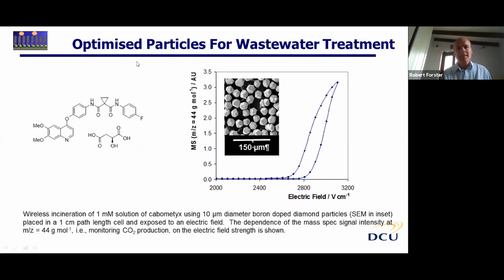One compound of interest is pharmaceutical drugs and metabolites, a growing problem in municipal water. We're looking at this drug, Cabometyx, changing the voltage on the feeder electrodes within the reactor. We're generating really intense electric fields, on the order of 2,000 to 3,000 volts between the two electrodes. It's important to realize that not all of that voltage drop is actually delivered to the boron doped diamond particles themselves - there will certainly be some loss.